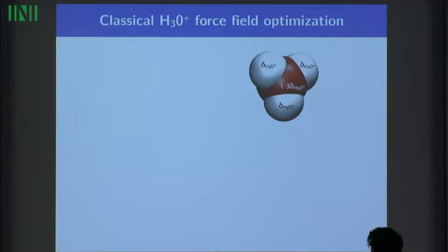And then we optimize these ions to reproduce the macroscopic thermodynamic variables. So this is a relatively uncommon thing to do. People typically use, for example, quantum mechanical calculations or other ways of optimizing these classical molecular force fields. We optimize them with respect to the macroscopic thermodynamic variables, because in the end it's macroscopic thermodynamics that we're measuring at all. And so it's the only thing that we actually care about. We don't really care about the molecular details of this molecule.